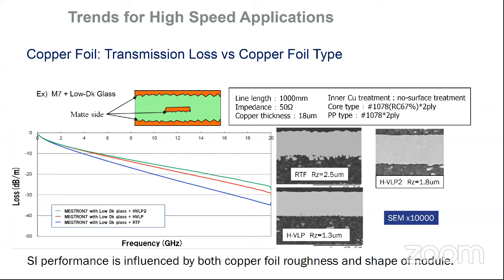So working very closely with your dry film supplier as well as your equipment and your pre-cleaning chemistry partners. That hey, I'm getting to a point where I'm using a lot of ultra low, very thin profile copper foil. Let's review my process and make sure that I can do this without losing yield points. So I think that's important. Yeah, RTF is very forgiving, but the smoother you get on the surface, the more difficult you're going to find with dry film adhesion.